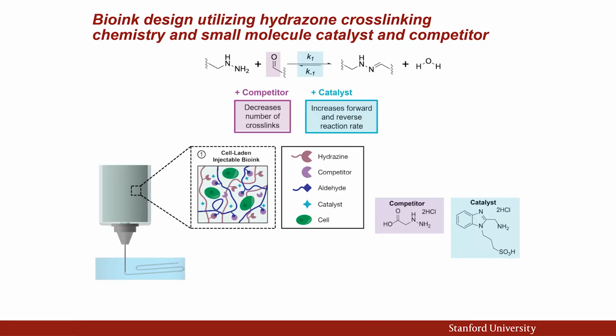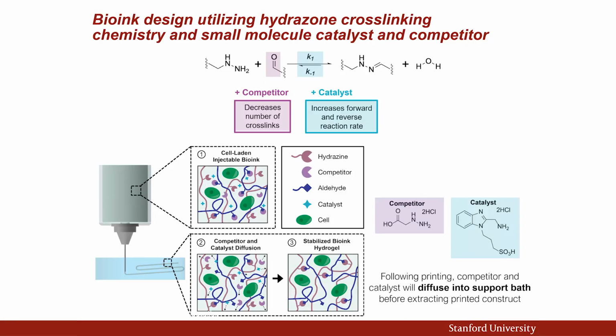So what if we now go in and begin to tune both the thermodynamics and the kinetics of this cross-linking reaction, right? We can use a competitor to block some of the cross-linking sites. So initially, in the syringe, we don't have a fully cross-linked network. And we can also use the catalyst to increase the forward and reverse reaction rate without altering the thermodynamic equilibrium constant of our reaction. So that lowers the yield stress, adding the catalyst. After it prints, these small molecules can diffuse out and your network can form, leaving behind a nice, robust gel.